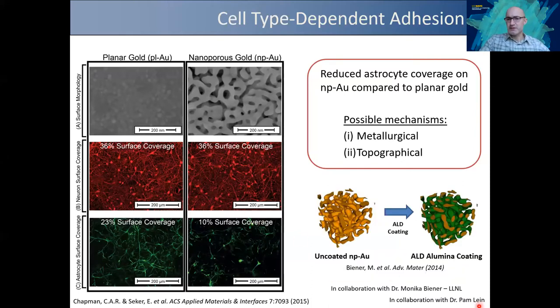We collaborated with Lawrence Livermore National Lab with Dr. Monica Biener and used a technique called atomic layer deposition, which is basically a purely surface reaction limited process where you can grow conformal thin film ceramics on high aspect ratio structures like this. It's really one of the few techniques you can do this with on high aspect ratio structures. So we grew aluminum oxide, alumina, a few nanometers of it along these electrodes, which in effect basically sealed the surfaces and switched the surface chemistry from gold to alumina, but maintained the same topography.